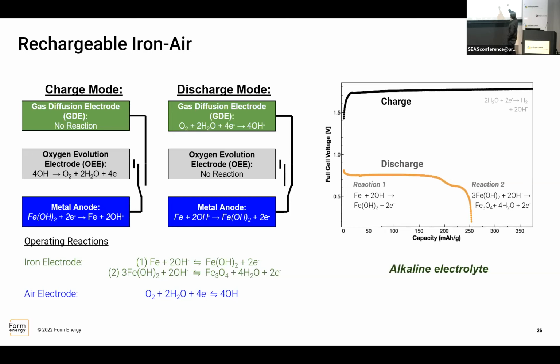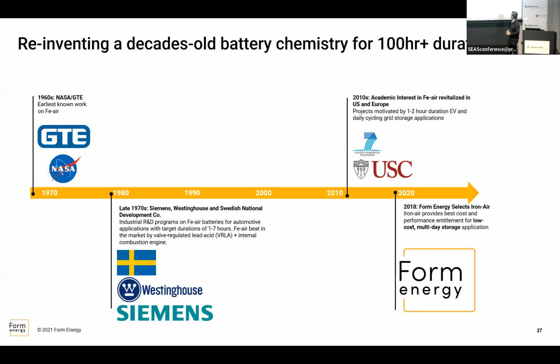Right? The second is that if you look at the capacity, you see that the charge line is longer. You're putting in more electrons to charge it than you're discharging. Another source of inefficiency. Right? And so what's that coming from? That's actually coming from the fact that the iron electrode's HER, hydrogen evolution potential, is pretty much the same potential at which you want to charge your iron electrode. So that's one of the challenges in this chemistry, is that when you charge the battery, at the same time, that iron electrode also wants to produce hydrogen. Right? And so, this is where a lot of the engineering and design and chemistry comes in. Right? And so these are, I'm being very upfront, these are the deficiencies of this system. But, for the long storage duration applications, it all still works.